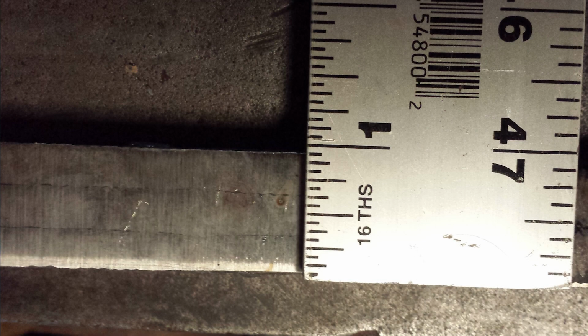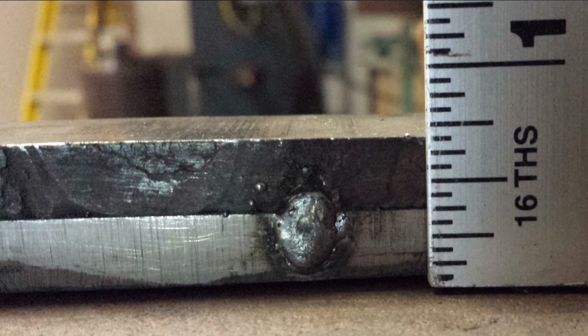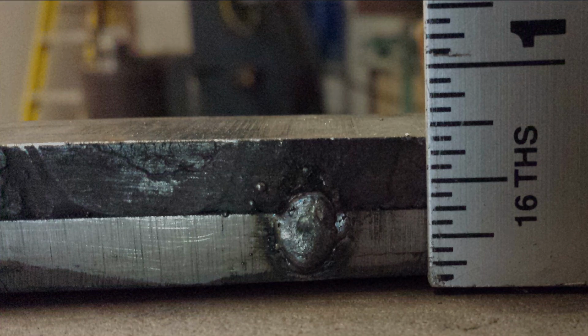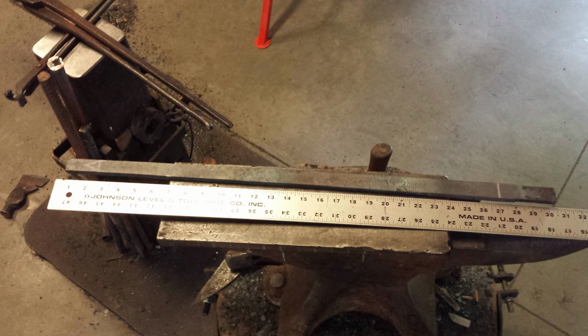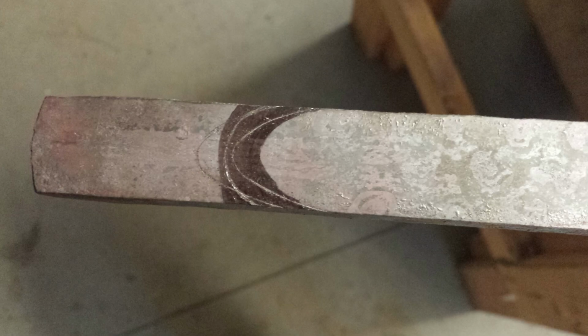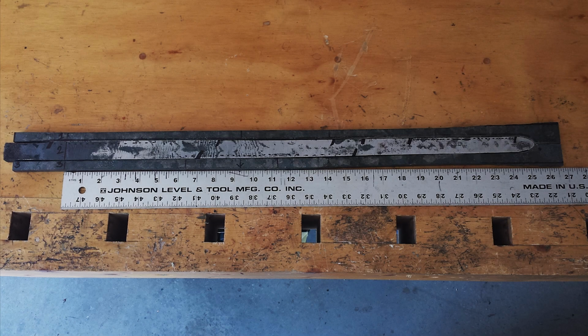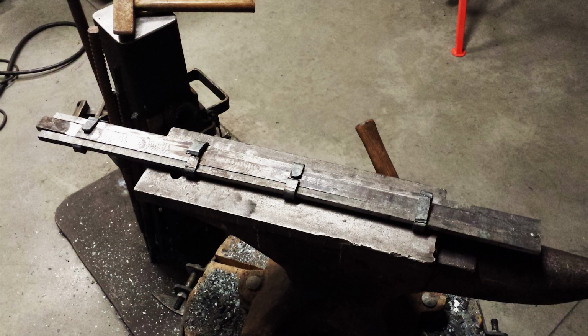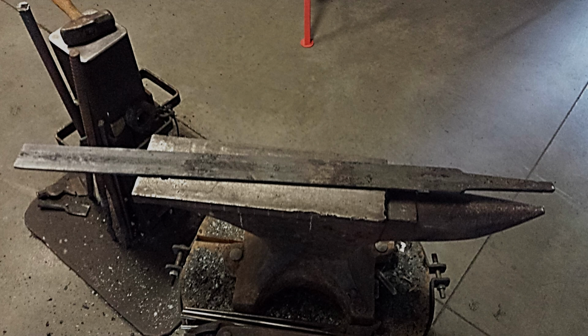This is what I thought the first time I looked at this, and what I set off to do in my first reproduction attempt. The core bars measure about 1 inch in width and about 3/4 of an inch in thickness. The length was about 27 inches, not counting what would become the tang. Some trimming was needed for the excess material from the tip. Here I am ready to weld the outer edges to the core. Bound tight and ready to weld. Welded together, and the tang has been forged as well.